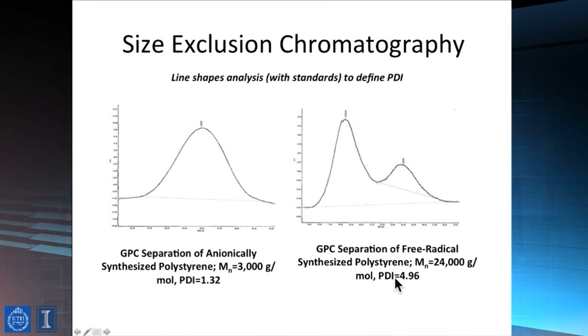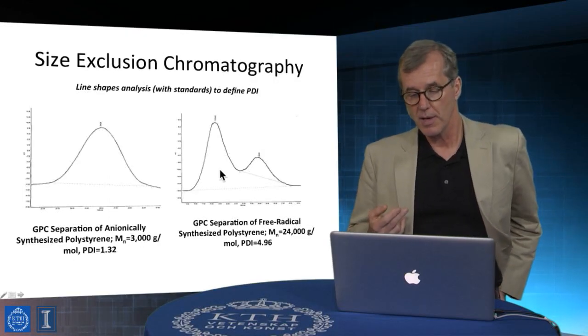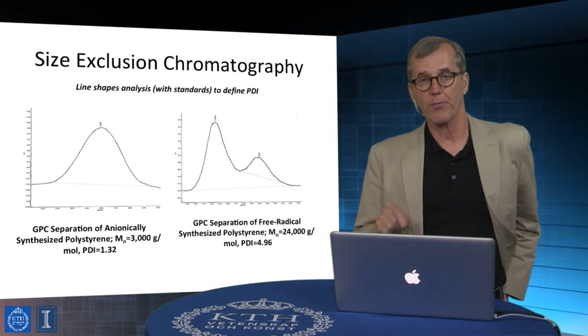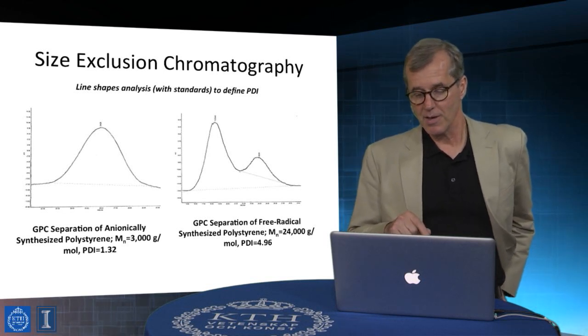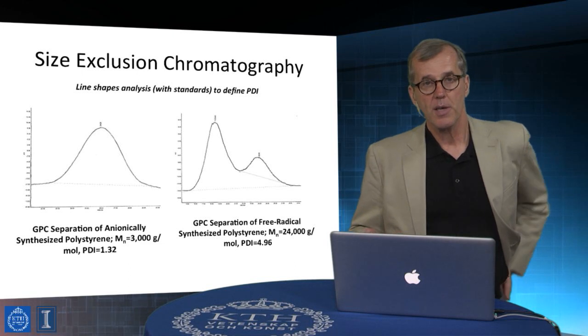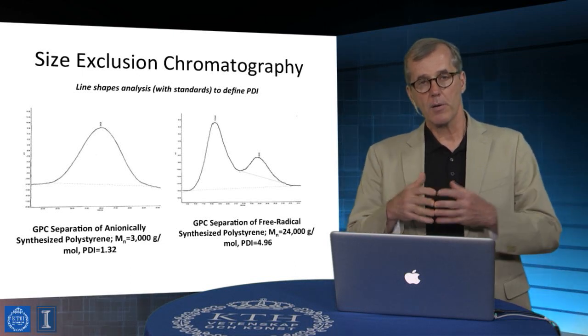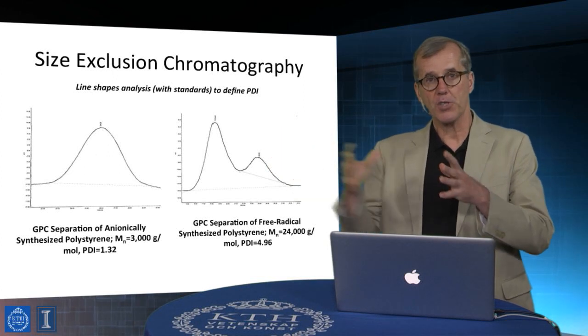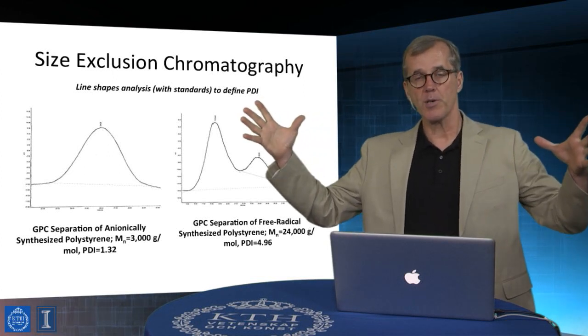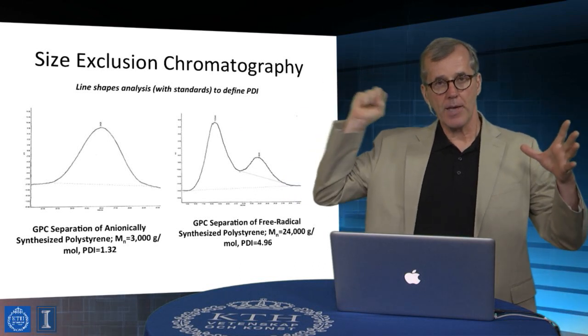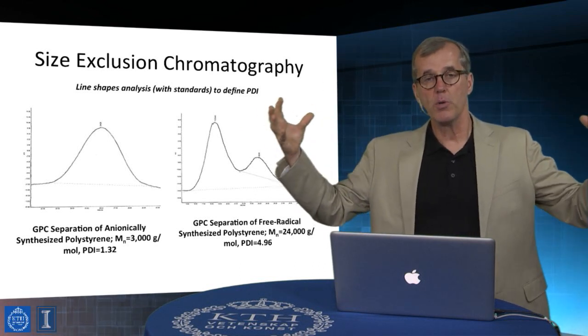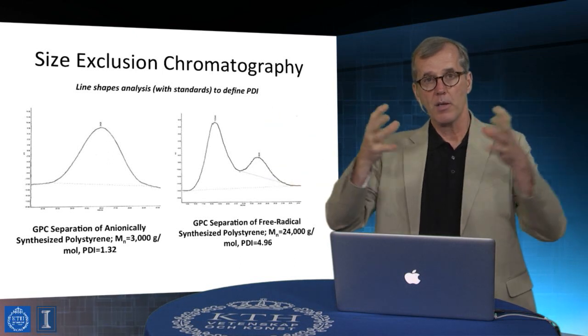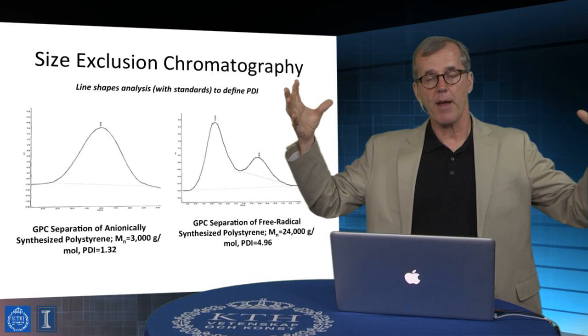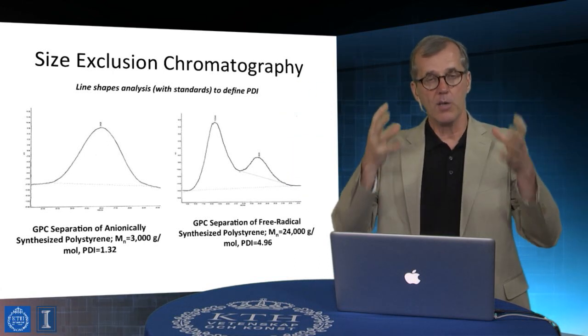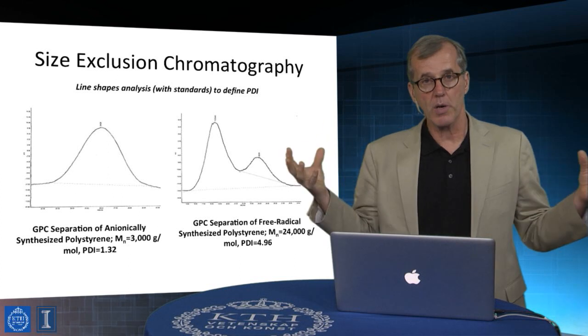And actually, when you look at this, the reason why the polydispersity index is so large is that it's actually eluting as two components. And this comes from the fact that this is a polymer made by free radical polymerization. And the way the mechanism of this reaction works is that when we make polymer, it grows by a chain propagation step where the molecule is becoming larger and larger. And then at some point, it kills itself. And it kills itself either by two of these propagating radicals combining. So we have two radicals of some average size that when they combine and kill two radicals, you now have one molecule that's twice as large.